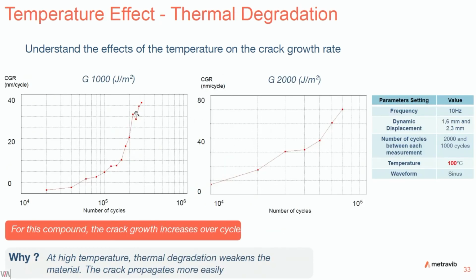And finally, I would like to introduce this curve. This is the crack growth rate as a function of the number of cycles at 100 degrees. We can see that the crack growth increases over cycles because we notice a thermal degradation of the material. And for sure, the crack propagates more easily, as you can see at different energies, 1000 and 2000, according to the number of cycles.